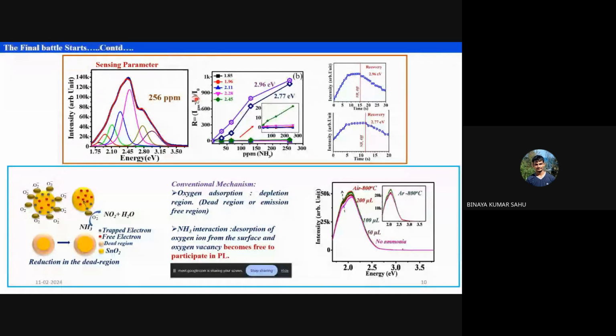So you have to do a little calculation, and this kind of spectra you can get, and you can see the 2.96 and 2.77 related peaks have enhanced very highly or very effectively as compared to the other peak. Here you can see the other peaks remain silent, but the other two peaks have seen an exponential growth, or they have increased drastically in the presence of various concentrations of the ammonia.